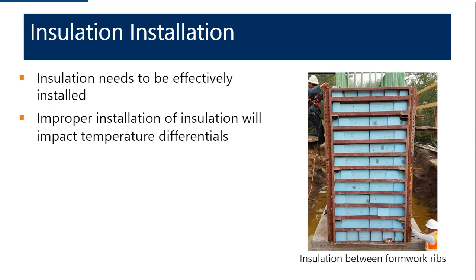This would speed up their process. The unfortunate thing in this particular instance is the type of insulation that they used was less effective because, for example, if you put in an R5, due to the placement of the ribs, it effectively was acting as an R2 or an R2.5. And if you do something like that, you have to keep that in mind.